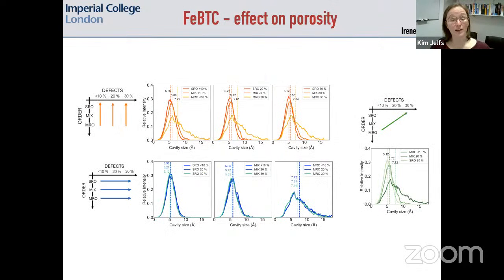And then we can also ask, does that tell us anything about the change in the porosity? I think this all intuitively makes sense, in that as you increase the amount of order, or put in larger secondary building units, you tend to trend towards larger cavity sizes. It's shown at the top in the orange colours, whereas changing the degree of defects is having only a very minimal effect on the porosity,